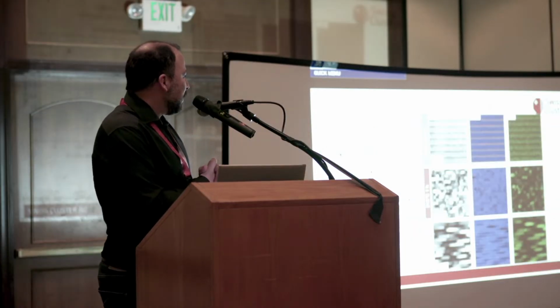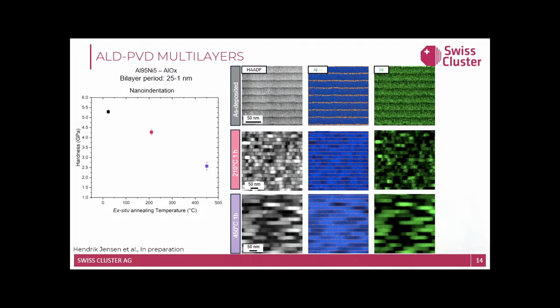So our partners at EMPA continue also investigating this grain growth mechanism in different types of coatings. So for instance, in this one, also an aluminum nickel alloy, going from the as-deposited, where you can really see the multi-layer structure in the TEM images and with the EDS. And as we go to higher temperatures, then you just have this very lateral grain growth, right? And depending on the material, depending on the thickness, of course, you can also tailor this type of effect. Similarly, doing the hardness testing, we can observe how this type of effect affects the mechanical performance.